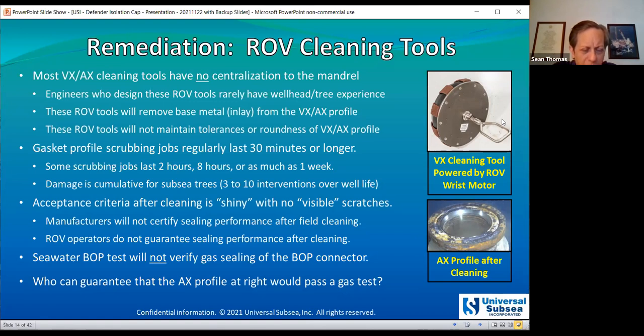So one really critical issue is that there's no way to do a dimensional inspection on a tree or a wellhead after it's on the seafloor, as we all know. And so the only acceptance criteria after these cleaning operations is a shiny surface with no scratches visible to the ROV cameras. And of course, the equipment manufacturers will not certify sealing performance after a handoff to the customer or any field cleaning. And similarly, the ROV operators won't guarantee sealing performance either. So we're left with a situation where there's really nobody accountable to ensure sealing integrity of this critical interface.